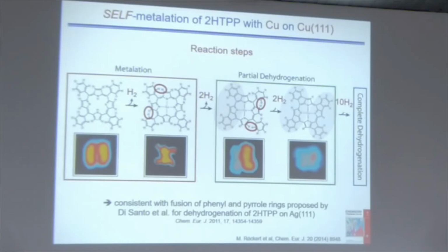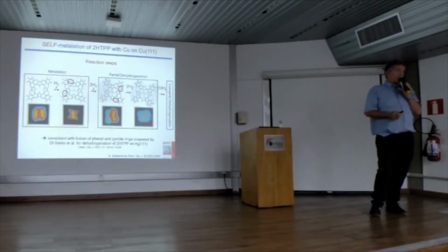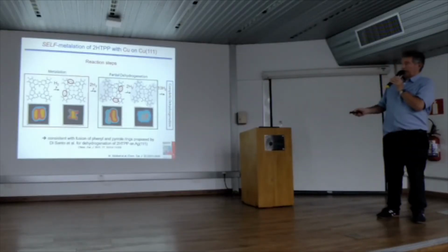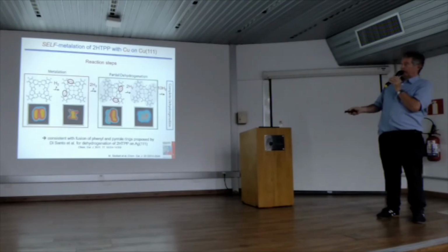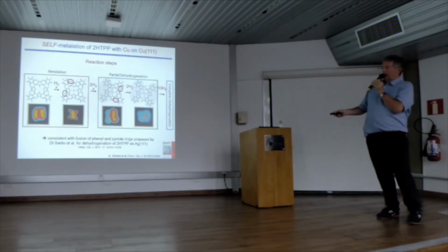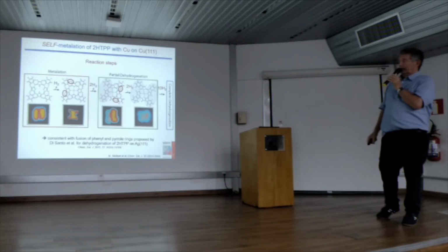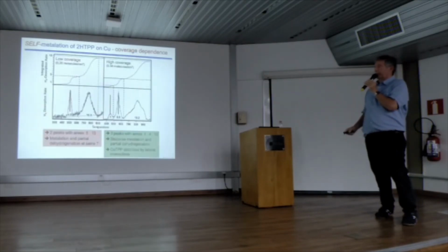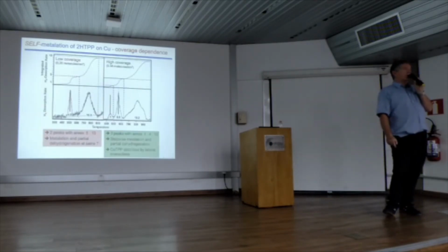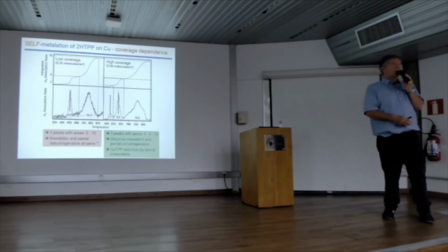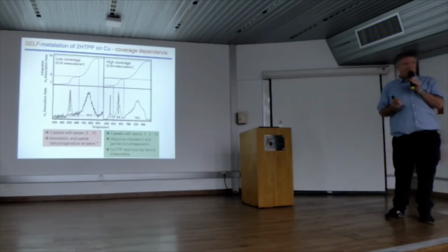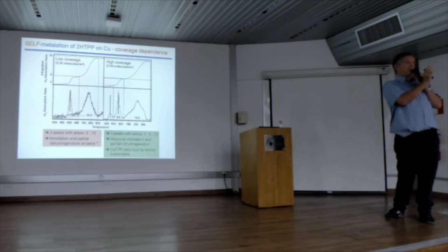So I talked about what's going on at the surface, but we can also watch these hydrogen atoms, actually molecules, released to the gas phase, and there's a technique that allows you to study that, and this technique is temperature programmed desorption. What you do is, it's not really that simple, you have a mass spectrometer, and you put the mass spectrometer in front of your sample, and then you have a glass tube